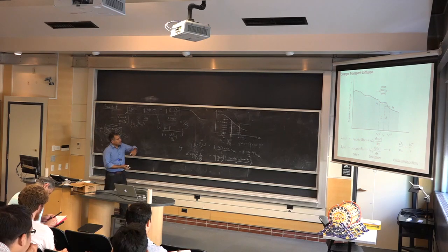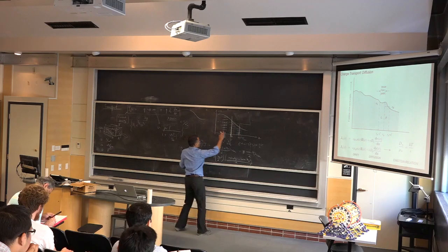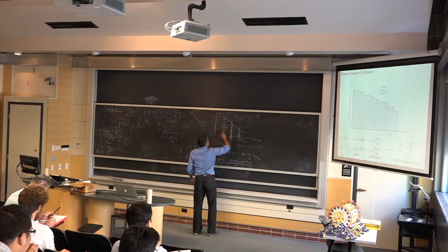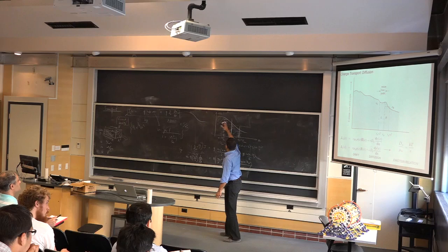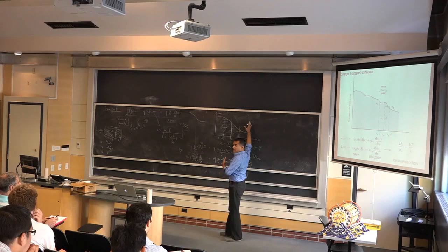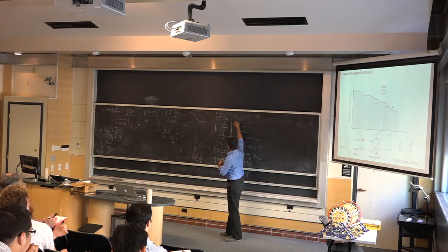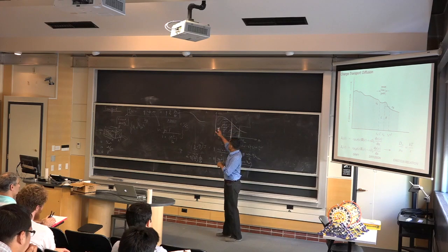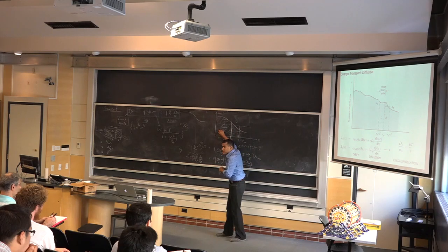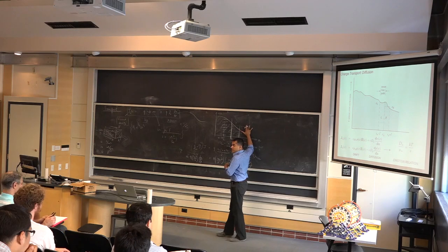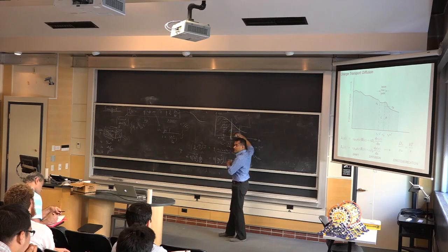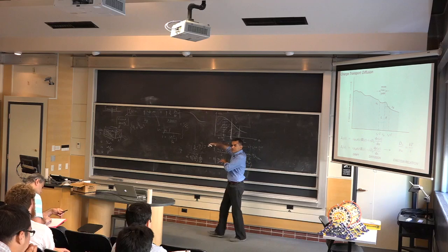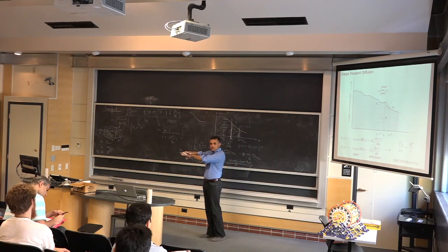So what will happen is, if I have such a distribution and I have not applied an electric field, I start with this sort of a distribution, and there'll be electrons that will flow this way, right? And there'll be a little current flow, but that is not going to survive for too long, right? Why? Because as you lose electrons from here, this part starts getting slightly positively charged. This part starts getting slightly more negatively charged because electrons are moving that way, and you set up an electric field. Right? And that electric field opposes this motion.